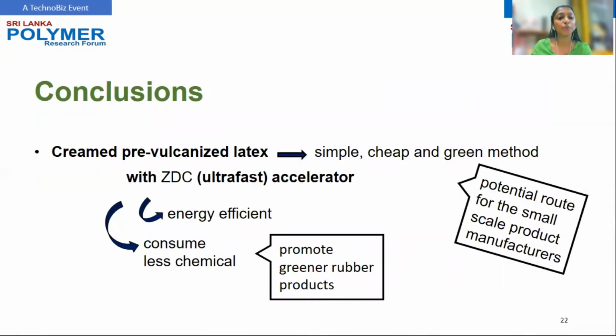Finally, let me give you the conclusion. When all the results obtained are considered, the pre-vulcanized latex made out of cream latex has shown better cross-link density and mechanical properties compared with that of centrifuge latex. Among the candidate accelerators, ultrafast accelerators showed the overall best performance. Therefore, it could be inferred that pre-vulcanized cream latex with an ultrafast accelerator system can be a new achievement for small-scale product manufacturers, assuring an energy efficient and less chemical consuming process, promoting greener rubber products.